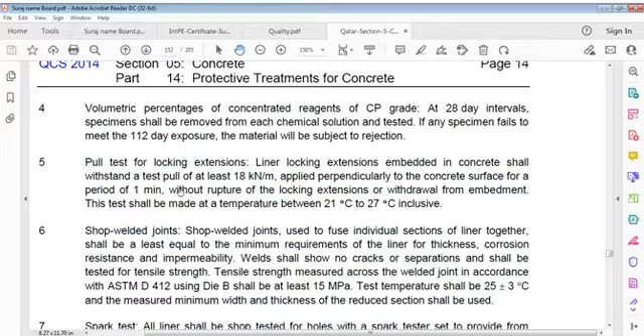If any specimen fails to meet 112 days exposure, material will be subject to rejection. It says volumetric percentages of concentrated reagents of CP grade at 28 days intervals, where specimen shall be removed from each chemical solution and tested. If a specimen fails to meet 112 days exposure.